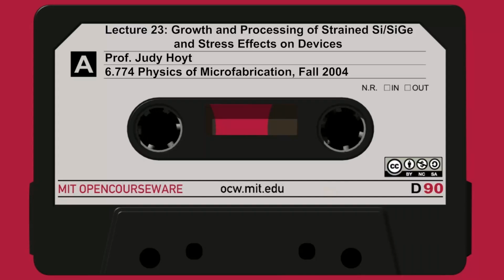If you do it on 30%, all of a sudden your diffusion coefficient is a factor of 5 or so higher. That's a big issue because you don't want the germanium diffusing into the channel. This data is not exactly interdiffusion data, and that whole problem needs to be worked out. But interdiffusion is definitely observed for about 1,000 degrees, 10 seconds at 20%. That's a no-no, so that's going to be a big issue in how we're going to activate source drains in those kinds of structures.